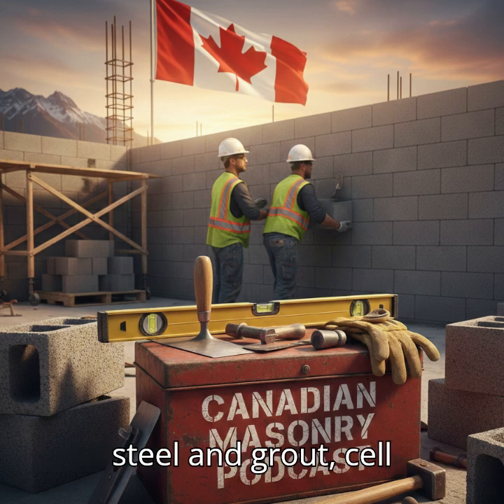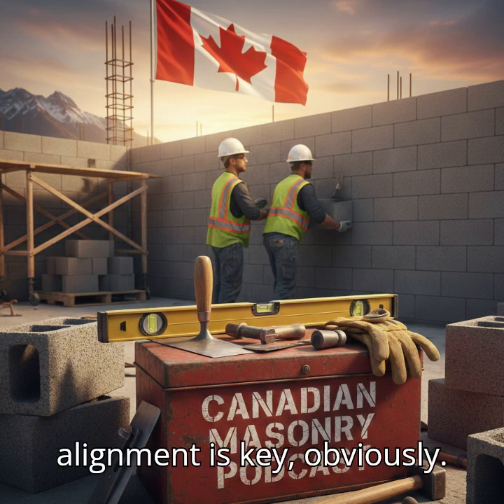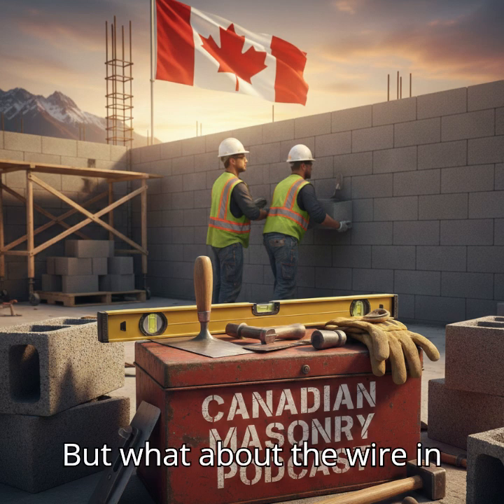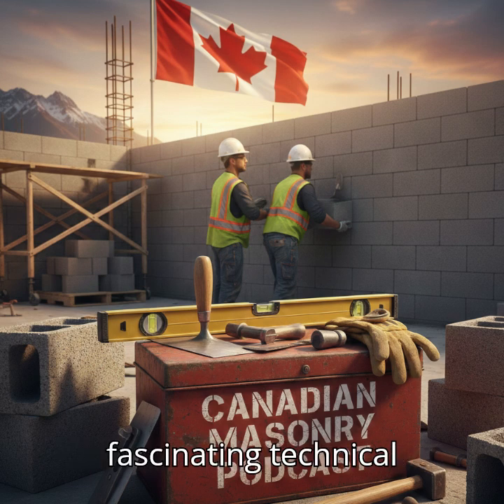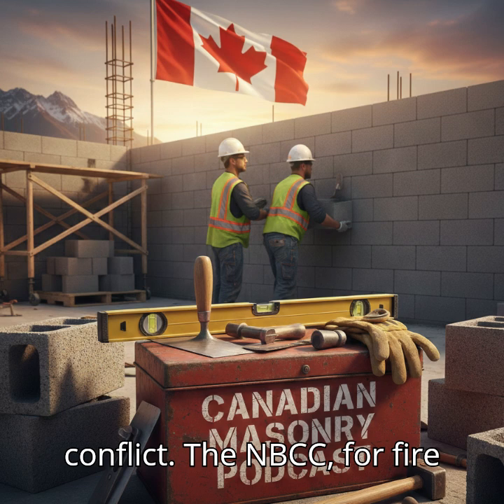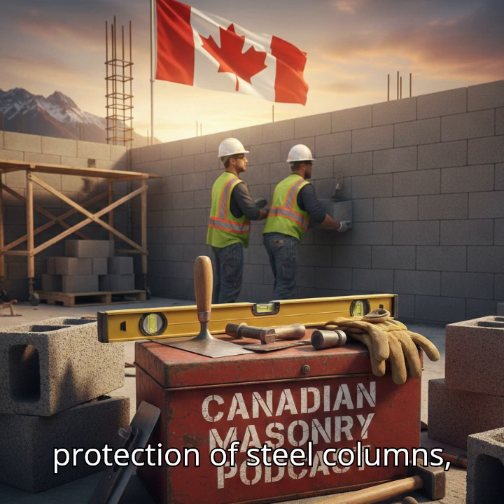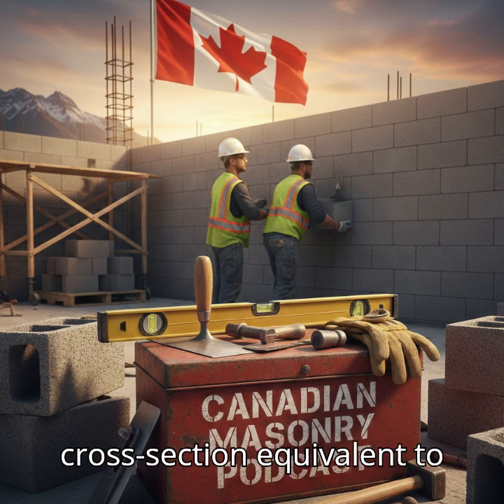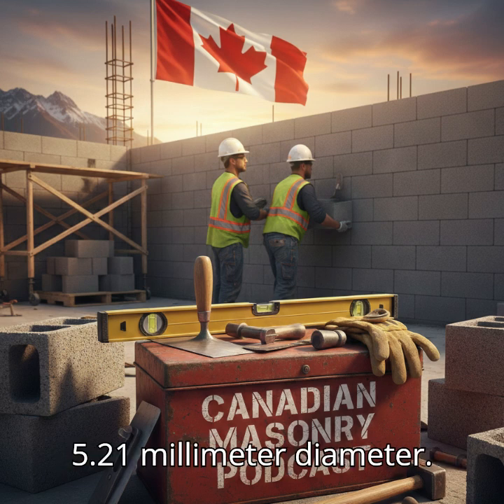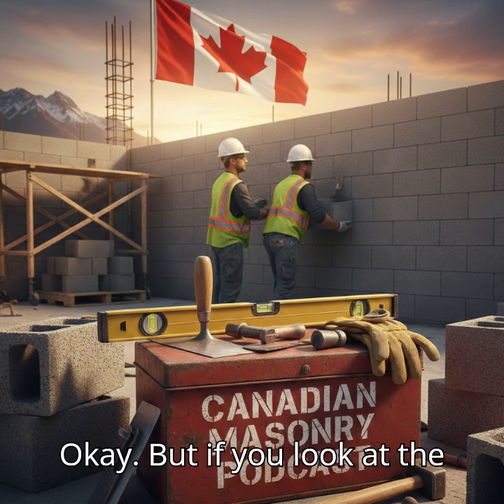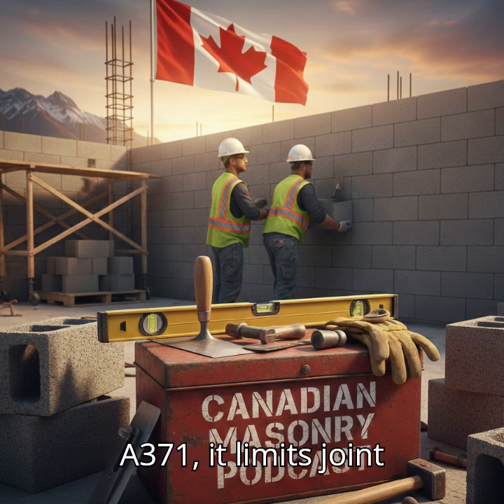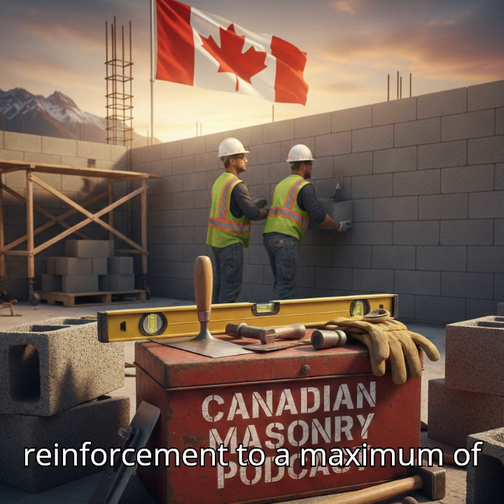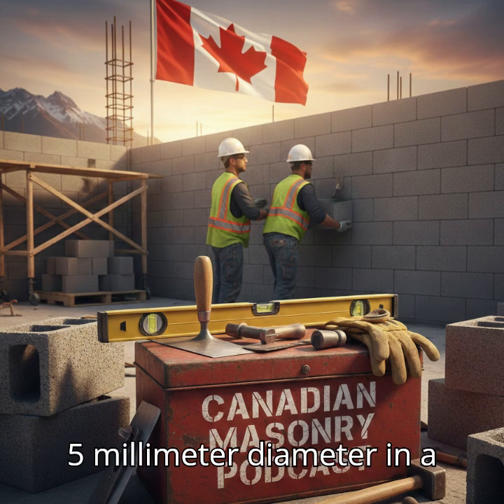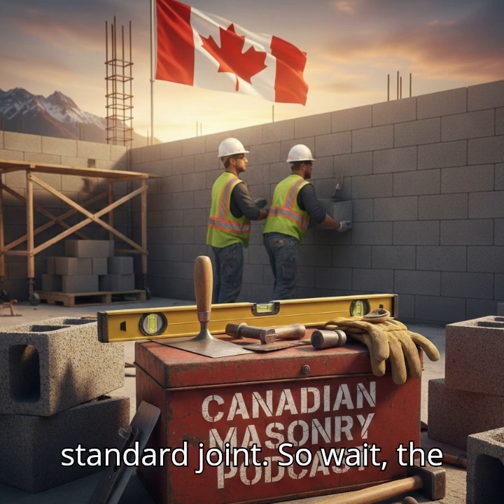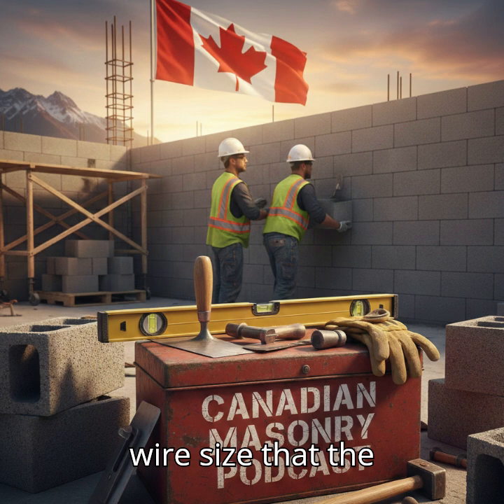When we need steel and grout, cell alignment is key, obviously. But what about the wire in the mortar joint? Here's a fascinating technical conflict. The NBCC, for fire protection of steel columns, might recommend a wire with a cross-section equivalent to 5.21 millimeter diameter. Okay. But if you look at the construction standard, CSA A165.1, it limits joint reinforcement to a maximum of 5 millimeter diameter in a standard joint. So wait, the performance code suggests a wire size that the installation code says you can't actually use. In the standard joint, yes.